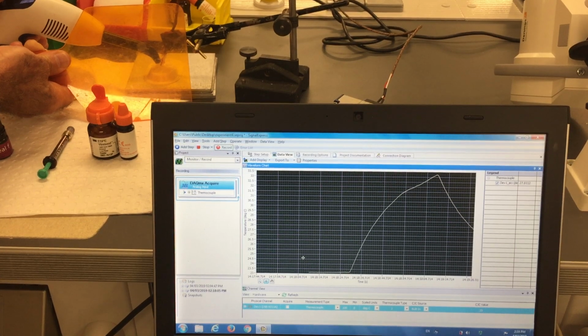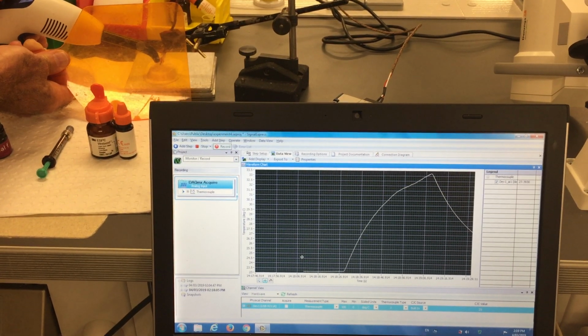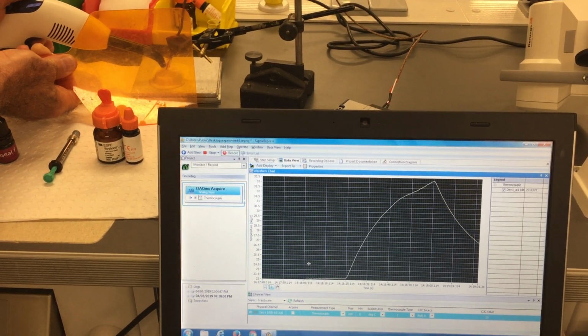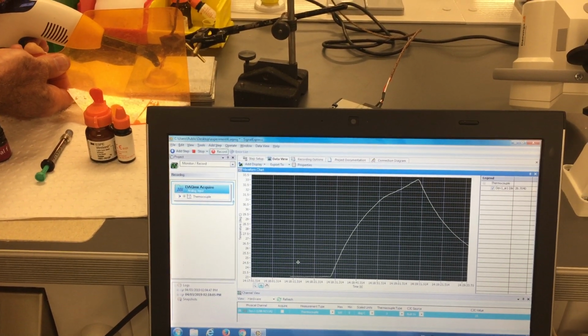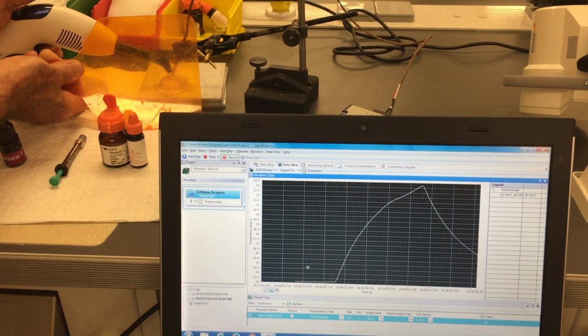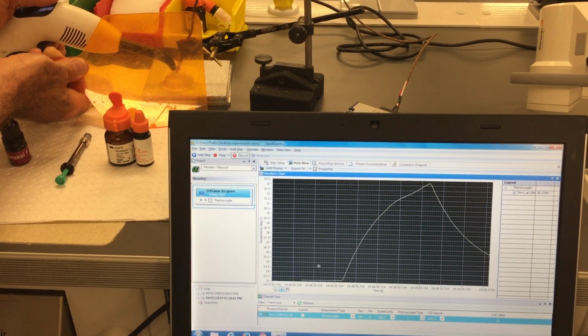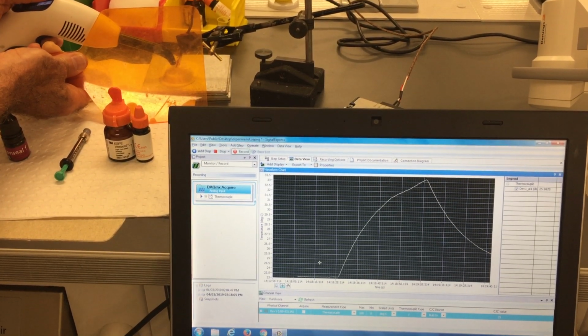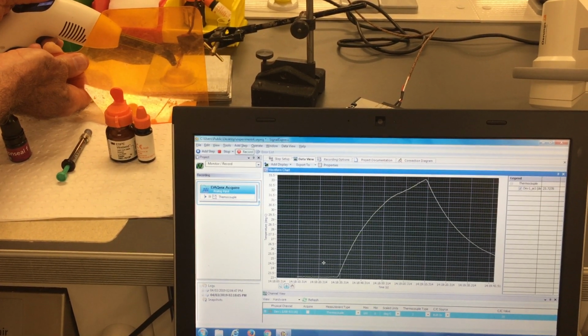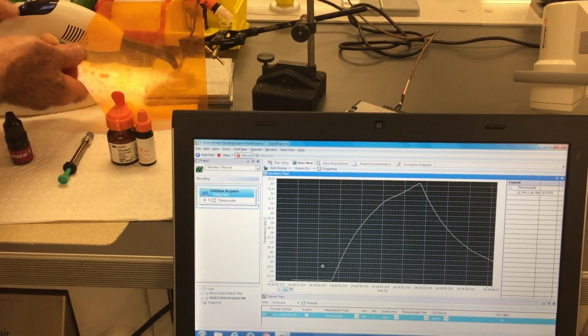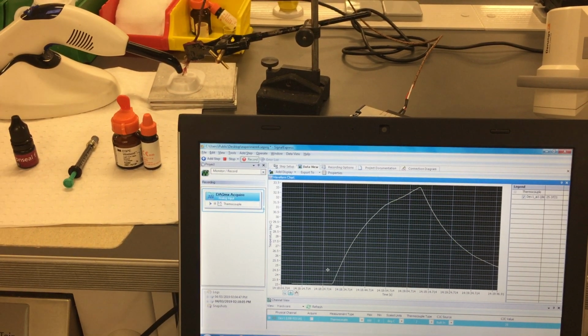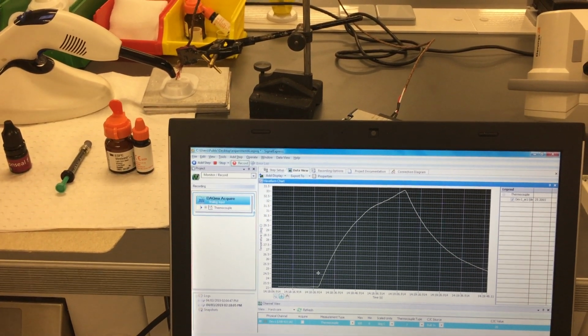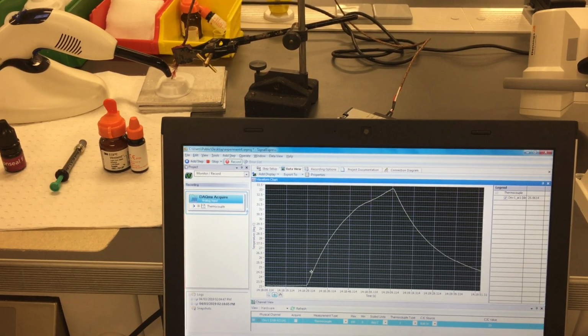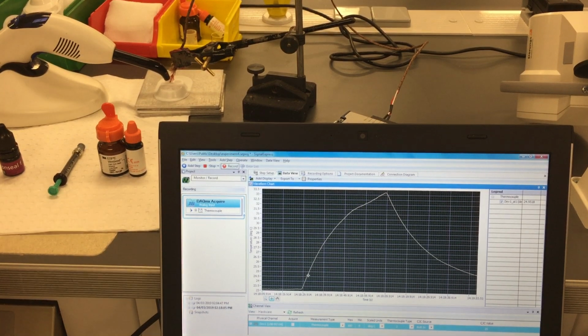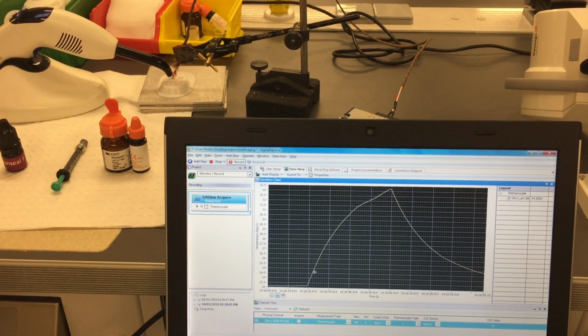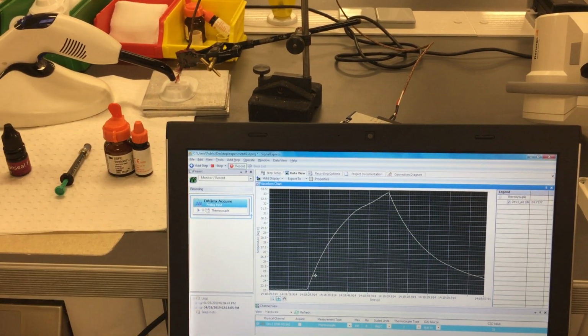Now that's turned off and you get the cooling curve. So this is without any material in there. With the material placed around the thermocouple, you'll find that the temperature goes higher. The more monomer there is to cure, the greater the temperature. And this is one of the things you need to be careful of. The pulp will be actually cooked if there's too much of an increase in temperature. The temperature of the pulp will only sustain about a 5 degrees increase before it starts to denature.